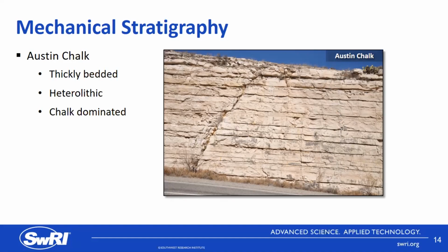It's relatively unfractured, with the exception of a tall fracture that's dipping towards the east here, and a tall fracture dipping towards the west here. These are actually both faults. This one has about 30 centimeters of displacement on it, and this fracture has about a couple centimeters of displacement. Very little displacement, but that allows the fracture to propagate up across all these mechanical layers. It's mostly chalk. It's 98% chalk or something like that, maybe 95%. But it's got these mud rock interbeds that are thin, but they're able to arrest the vertical propagation of fractures. So thickly bedded, heterolithic, but chalk dominated.